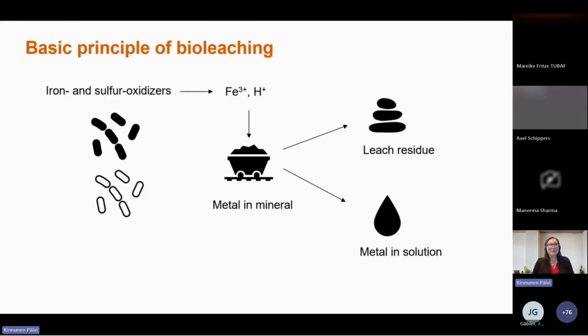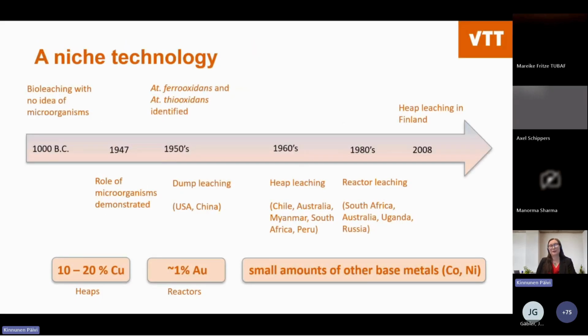Okay, great. So basically, this is the very simplified principle of bioleaching. We have different kinds of iron and sulfur oxidizing microorganisms, and they are able to oxidize iron to ferric iron, and then they are able to oxidize different kinds of sulfidic minerals. In this way, they produce ferric iron, which is a leaching agent, and they also produce an acidic environment. These leaching agents then leach the metals from the mineral so that we get the metals into the solution, and then we have a leach residue. This is a very simplified picture of that.